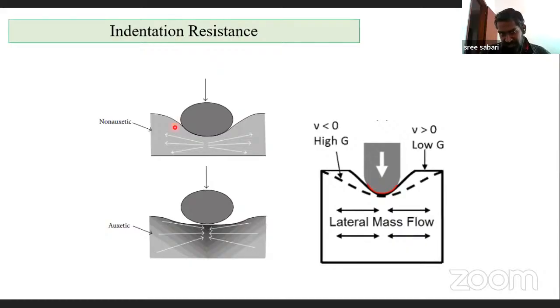Even in this schematic representation, you can see that nearly 1/2 of the radius, the indentation is nearly to the radius of the ball, whereas here you can see that the indentation level is very small. Even 1/3 or 1/4 part is only indented from this surface. You can relate it with the initial surface. So here, if I draw a straight line, nearly half of the ball is inside the material, whereas here only a little amount of the material is deformed because of this indenter.